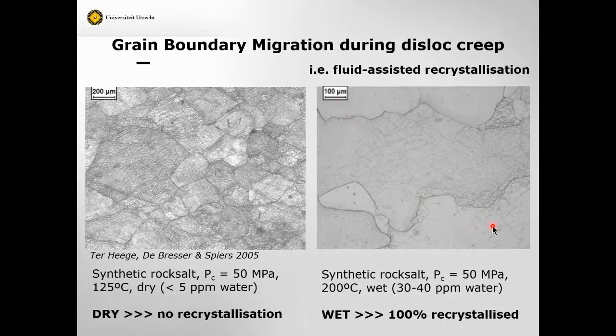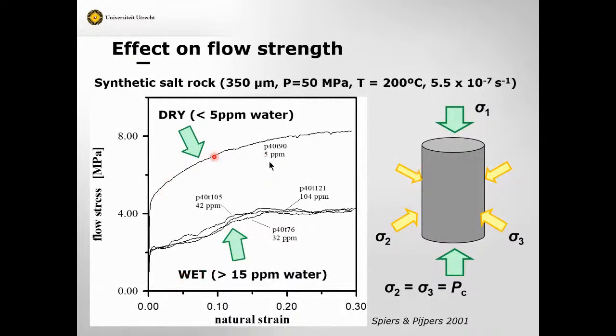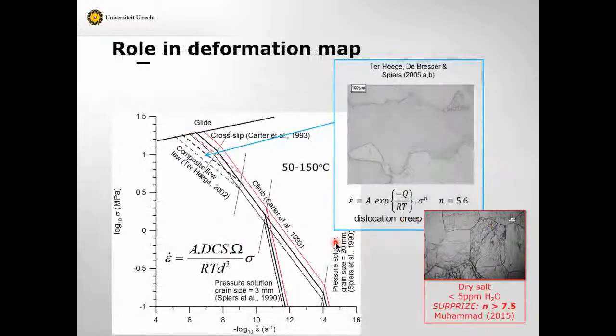The microstructure is totally changed by new crystals growing. That happens because fluid in these thin films acts as a medium through which deformed grains dissolve, and then the material precipitates on the other side, so the boundaries grow, and new strain-free crystals grow. This changes the microstructure, but also affects the mechanical behavior, so we need to know the conditions under which it occurs. Look at this. This is a dry material stress-strain curve, constant strain rate experiment, elevated pressures, no dilatancy. If you have just a few, maybe 10, 20 ppm water present, the flow strength is reduced by a factor of 2 because of this recrystallization effect.